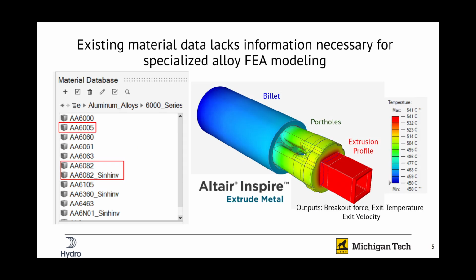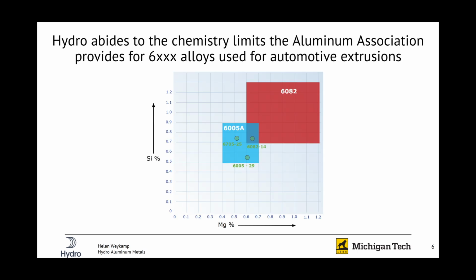The existing material data in software like Inspire Extrude only have very generic aluminum association standards such as a 6005 or a 6082 alloy, rather than having the specialized compositions that a billet supplier like Kehoe is able to produce. And we're using this simulation software to try and model the breakout force, exit temperature, and exit velocity of these alloys in extrusion conditions. Kehoe's specialized billets fall within the 6005A and 6082, and as you increase your silicon and magnesium concentration, you're going to be seeing increasing strength while also seeing a decrease in that extrudability.